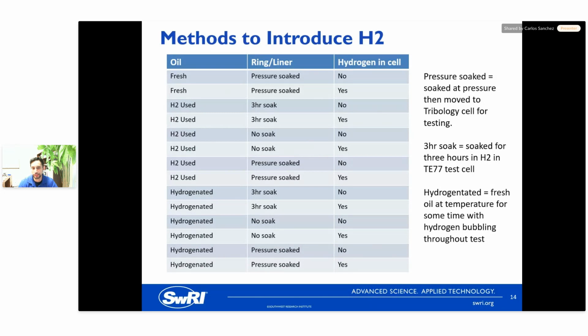We also worked with other hydrogen groups to actually impregnate the hydrogen into our engine parts as well. So one method we did was actually put the engine parts into an autoclave with hydrogen for a certain amount of time, took them out of the autoclave and placed them in our cell. We found that the hydrogen actually dissipated pretty quickly and we didn't really see any effect, and it basically ran like a normal set of parts.